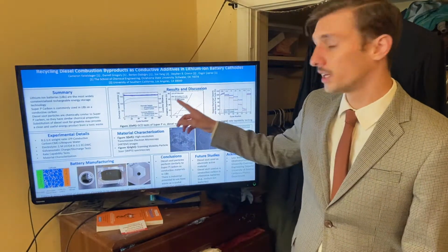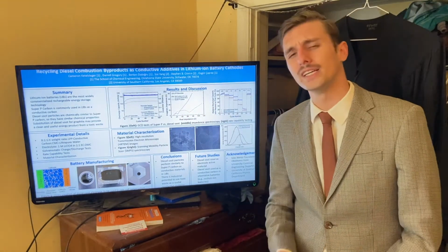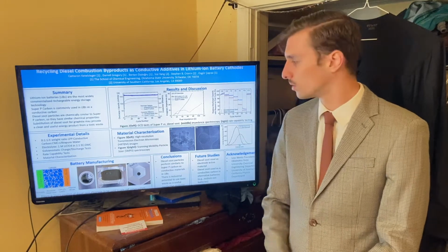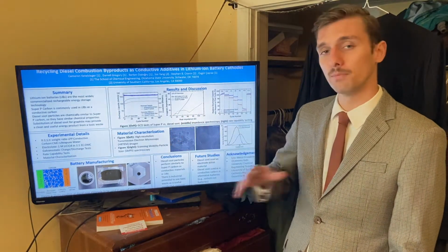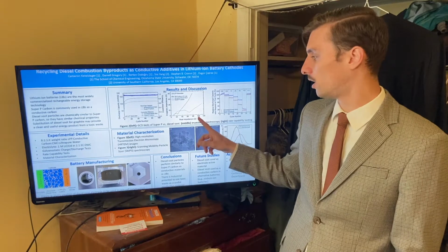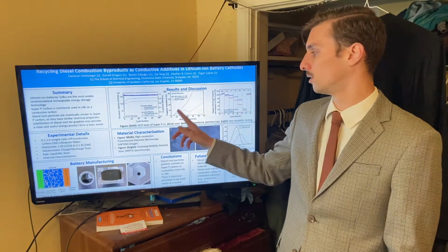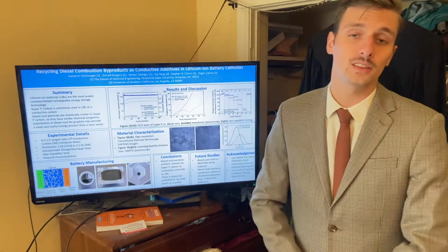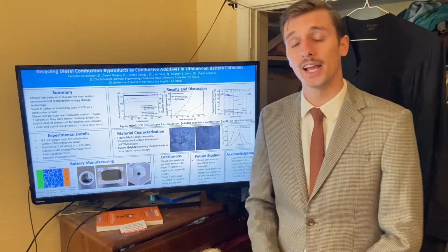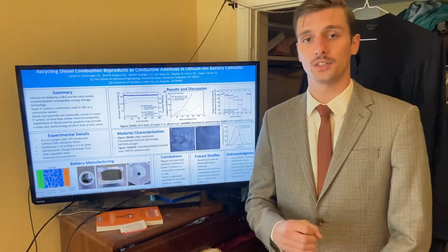So regardless, we conducted impedance spectroscopy to determine the internal resistance within our materials. While these are slightly different, the main fact here is that they're both under 100 real ohms on these humps. And that just simply means that there is little internal resistance and that our data that we've collected is solid.